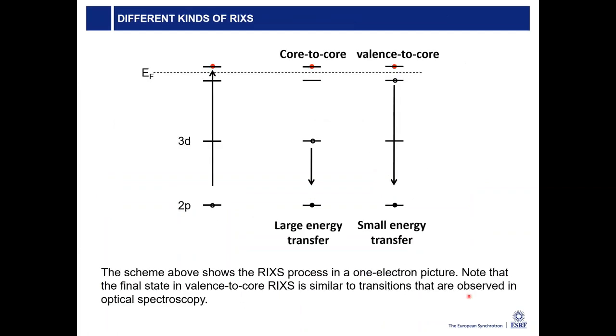And that I show here. So if another electron from 3D goes down to 2P, that would be a rather large energy transfer. If you have a transition in the second step from a valence orbital down to the core hole that you created before, the 2P core hole, then you have a net excitation that looks like you excited an electron from the valence orbital to an unoccupied orbital. And this looks like an excitation that you can observe in optical spectroscopy with a UV-Vis spectrometer, for example, in your lab, or even a Raman spectrometer in your lab.